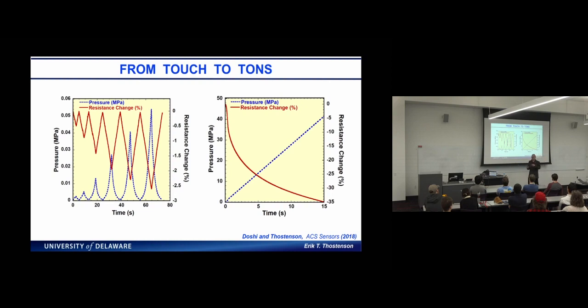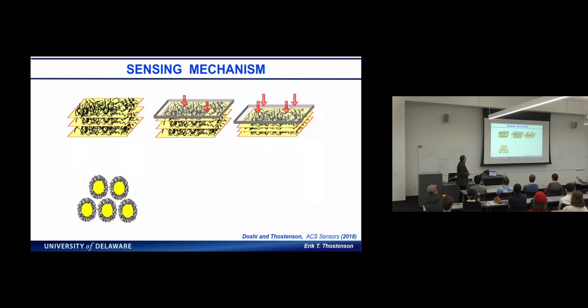It's because of the mechanism of how the sensor works. And we've done a lot of studies looking at and understanding how this sensor works. But this is just an example where we're ramping up the pressure, from very low pressure to very high pressure. And the resistance change actually is nonlinear, but that's what gives us our really wide sensing range. And we can calibrate that and do a curve fit.